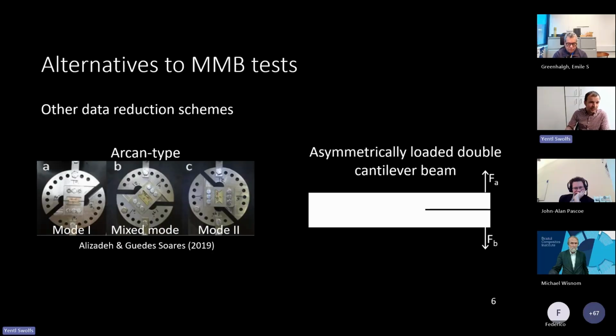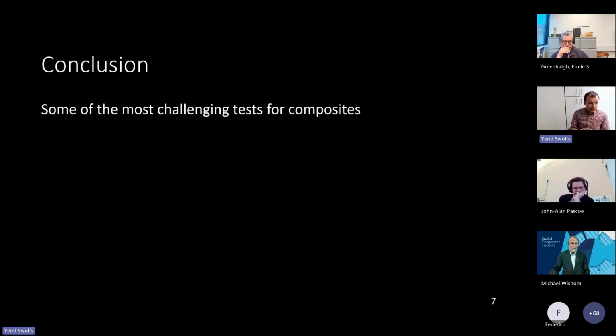Another alternative is to use a symmetric specimen, but then load it asymmetrically in a double cantilever beam. So essentially one of these two forces would be larger than the other, and in that way you also introduce a mixed mode 1 and 2 combined together. If you look overall, you can see that these tests are some of the most challenging ones that you can execute on composites. It also tends to be rather difficult to extract the data. You need to know very well where the crack is, how long the delamination is, what the shape is, and it's very often not a straight delamination front.